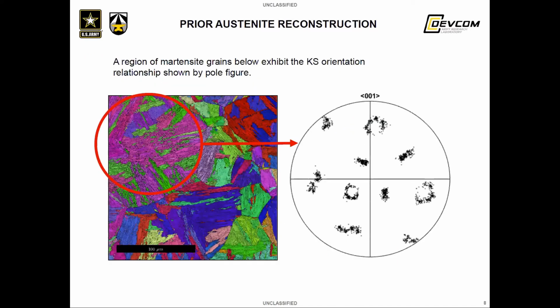Just to demonstrate this directly with actual martensite orientations, if you take the left image, which is the same set of EBSD data shown earlier, the region of pink and green laths in the top left have been collected and their orientations have been plotted in the pole figure on the right. You can see the same circles and bars configuration that's typical of the Kurdjumov-Sachs orientation relationship. Again, the orientation of the austenite grain that would belong to that region would be defined by the 100 poles that would lie right at the center of those three circles.